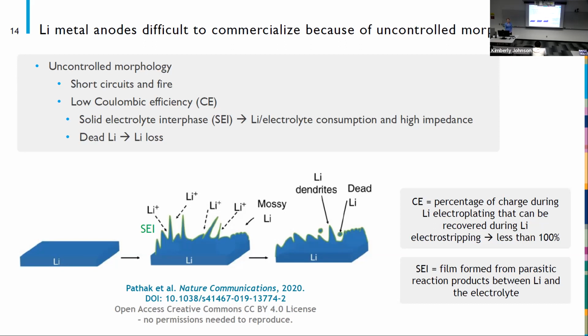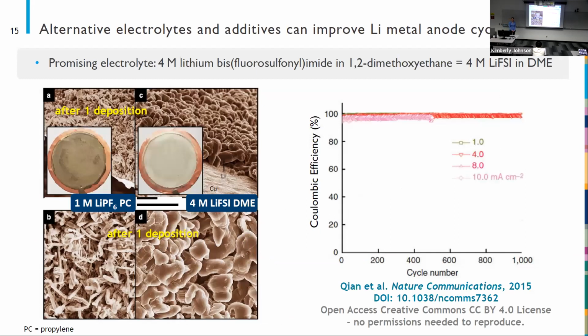So that SEI formation leads to irreversible lithium and electrolyte consumption. So we lose some of the material in our battery that's active. And it also leads to high impedance in these cells, which can also be a problem for trying to run them at high power. The other way that we can lose lithium is that we can form dead lithium, where the lithium that forms in these high aspect ratio structures can disconnect and become not connected to the current collector, so that we can't change it back to strip the lithium and make it ions and electrons anymore. So those are some of the problems that the community wrestles with lithium metal anodes.